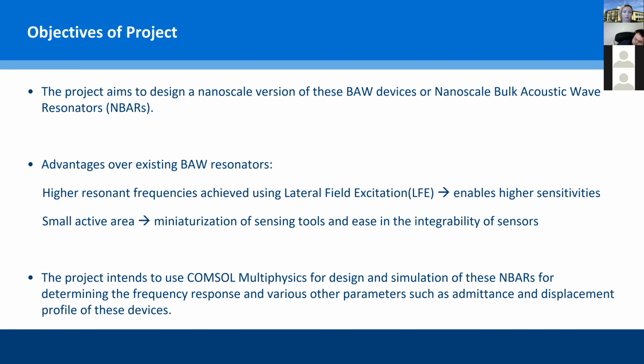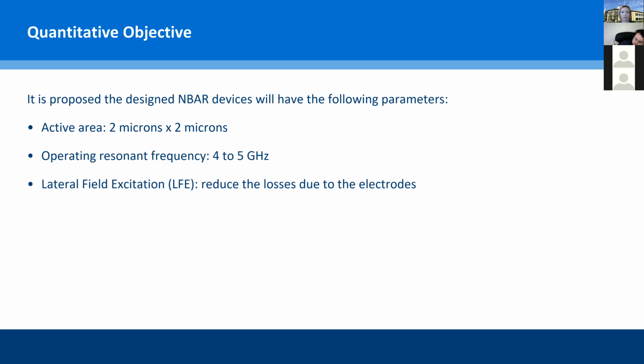For simulation, we have used a film of thickness 200 nanometers, but in reality, I think we would be able to go far below this. This was just to enable higher sensitivities, and the active region that we have used for our device is a few microns, which I will discuss. To design this device, we have used COMSOL Multiphysics, and I will discuss the boundary conditions that we used to simulate the profile of these devices.